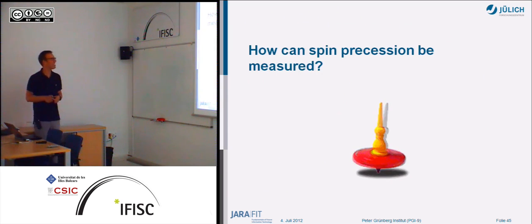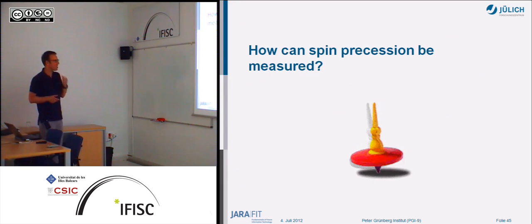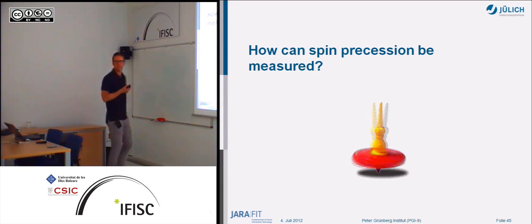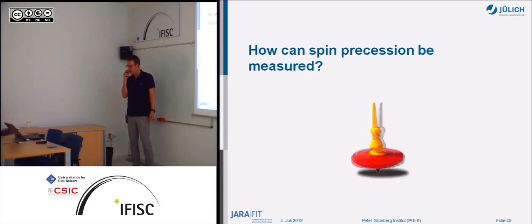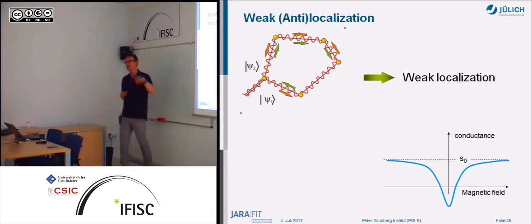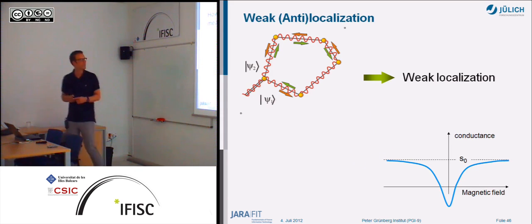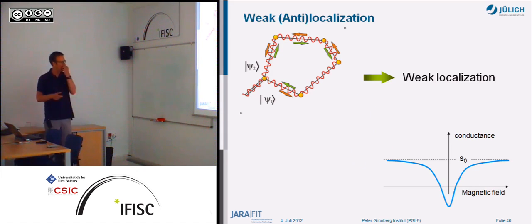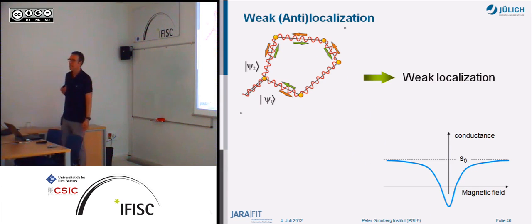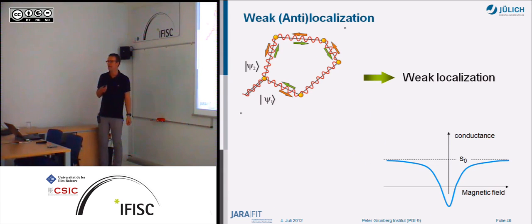So how can we measure the spin precession in these nanowires? That's what we would like to know. We would like to know how the spin is precessing in these nanowire structures, and we're using weak anti-localization for that. Weak anti-localization is an experimental technique where you can get information about the strength of spin-orbit coupling.